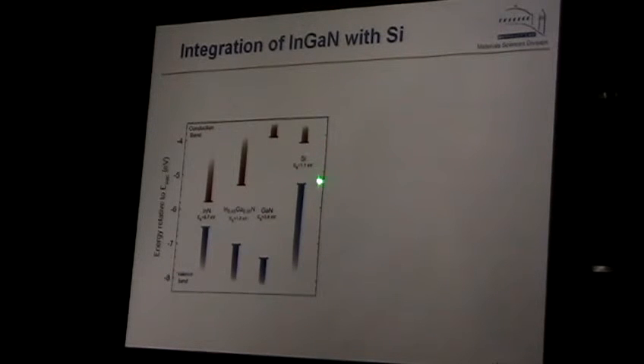The silicon band gap is 1.1 electron volt. So the valence band of silicon can be matched with the conduction band of a material with a certain composition, and in this case it is 45% indium. This alignment is very unusual, because it means that the n-type conducting material can be aligned with p-type conducting material. So that was an interesting possibility. However, the problem was now you have to grow gallium indium nitride on silicon. And this is not an easy task.